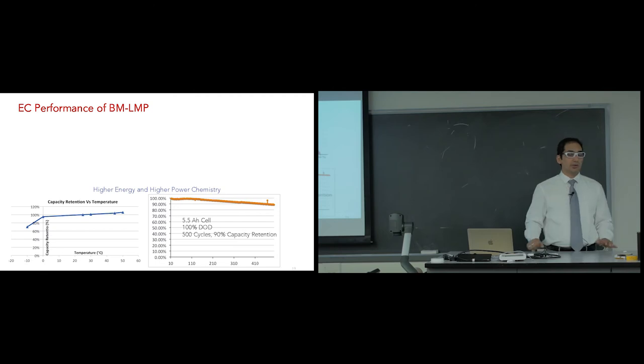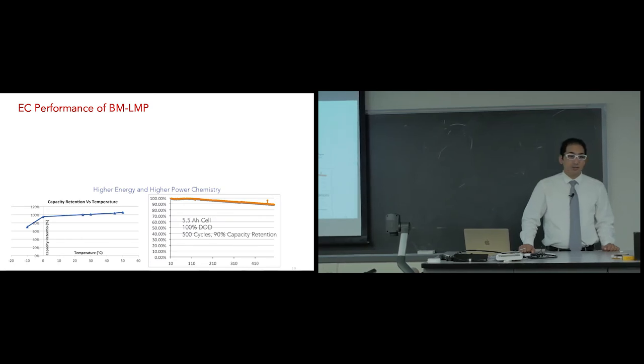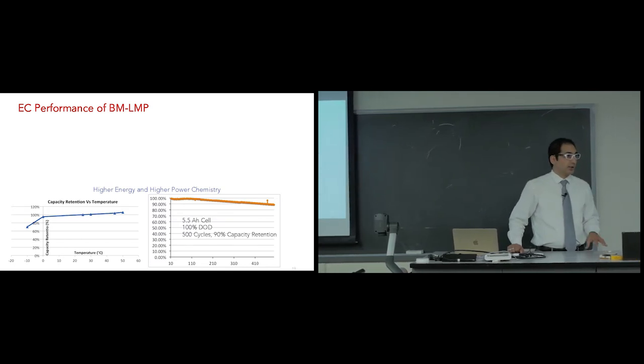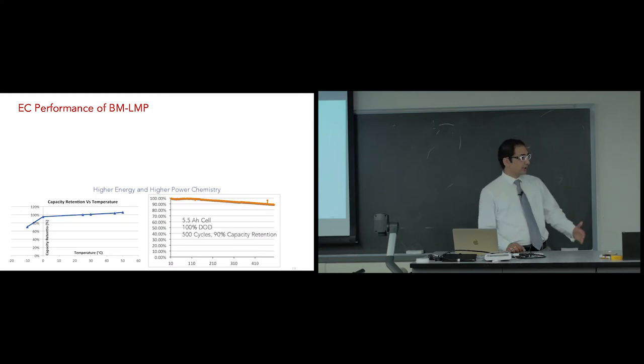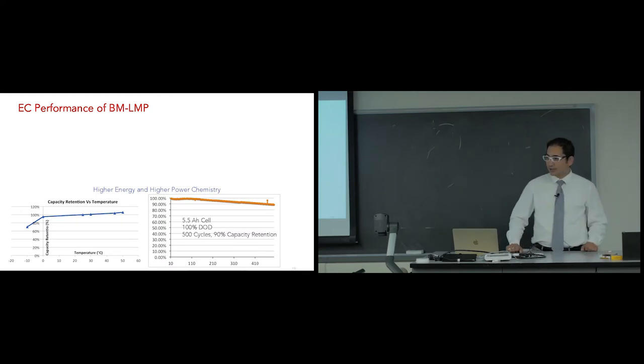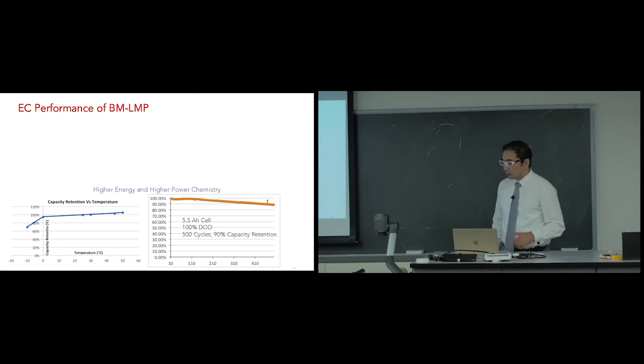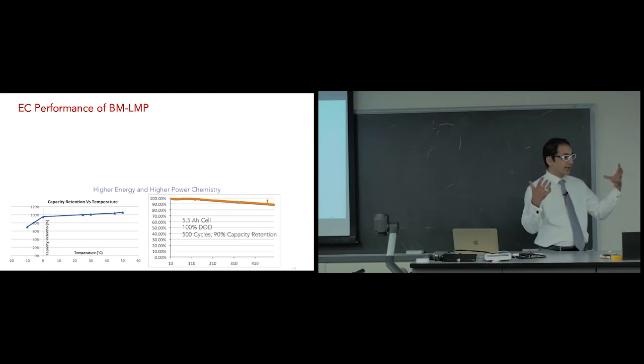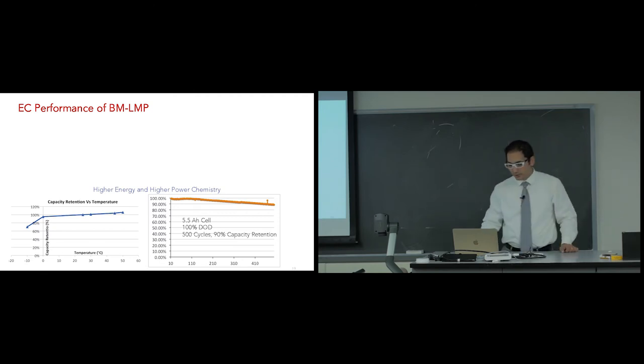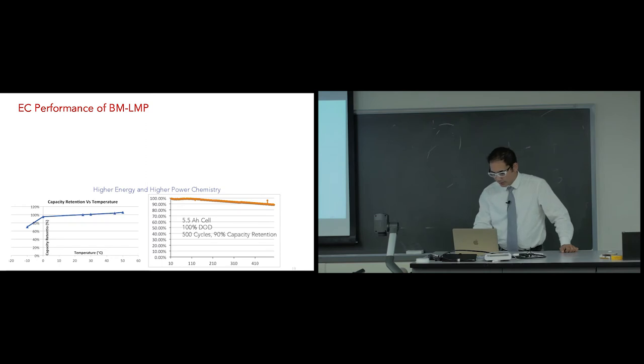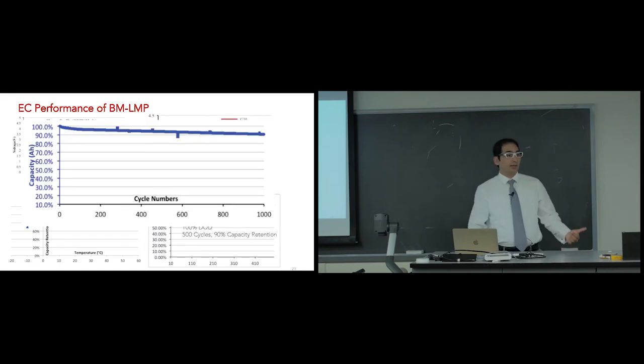If we look at all the commercial materials available in the market, we have the highest voltage per cell, the average voltage we can extract from each cell. It's about 3.9 volts. If you look at LFP, that's 3.2, NMC 3.7, and NCA 3.75. So we are about 3.9 volts. Higher voltage also means a lower number of cells to get the same voltage level, which is important in the industry. We can fine tune that again for high energy, high power, longer life.